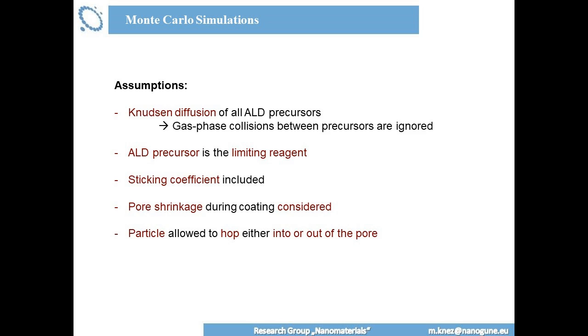Also, something which is very important, as I said before, the aspect ratio of the pore defines the exposure time which you need. But during coating, you are shrinking the pore. It means you are enlarging the aspect ratio. So in principle, if you want to make a perfect process and you are giving the exact amount of precursors which you need, you will have to have a dynamic process. That means a dynamic process which with every cycle or every 3 cycles is going to extend the exposure time, because you will need more, just because the aspect ratio grows.